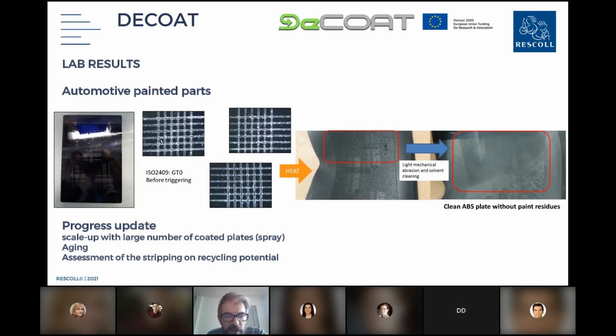For the automotive painted part, I will just present a very quick view of lab results. You can see on the left the picture of the painted part. It's ABS painted with different layers of classic automotive paints. We have very nice adhesion at the beginning. Then once we apply the heat, 150°C for less than 5 minutes, and it can be improved of course, we get a very nice blistering of the old paint layers and easy removal with light mechanical abrasion and solvent cleaning afterwards. You can easily achieve very clean ABS plates, easy to recycle afterwards. Now we're working on scale-up with a large number of coated plates, aging, and assessment of the stripping and the recycling potential, as presented by Vincent.